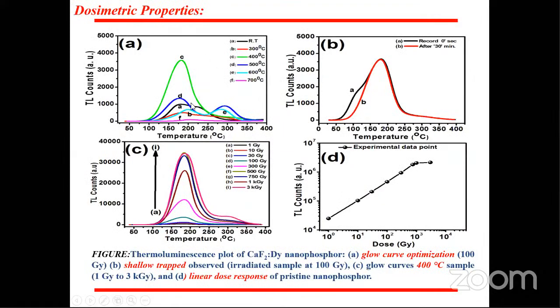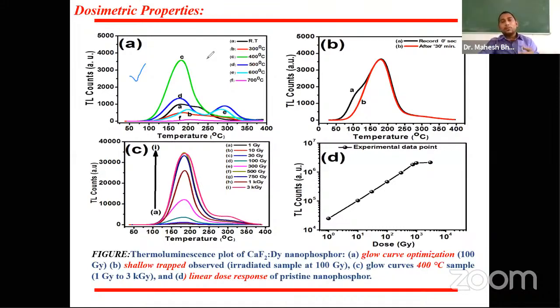This is the thermoluminescence spectra, primarily irradiated before the ball milling time. Before developing our phosphor material, we annealed the sample at different temperatures and got a very interesting behavior. We got high sensitivity at 400 degrees Celsius, so we chose that annealed sample for further analysis. After that we also erased the shallow traps. Figure A indicates the shallow trap, and B indicates after reduction of shallow traps.